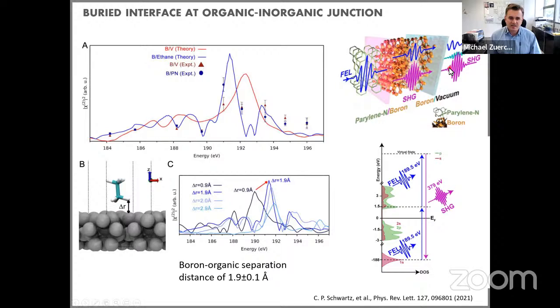This is another example of how you can arrange the geometry of these experiments to study specific interfaces. And what we did is we compared the boron-vacuum interface to the boron-parylene interface. And what you can see in the data is that in the case of parylene on boron, we see a shift of the spectrum as compared to vacuum by roughly 2 electron volts. So we see a slight shift of the spectrum in the second harmonic response of the system. And by doing simulations, we confirmed that this was expected.